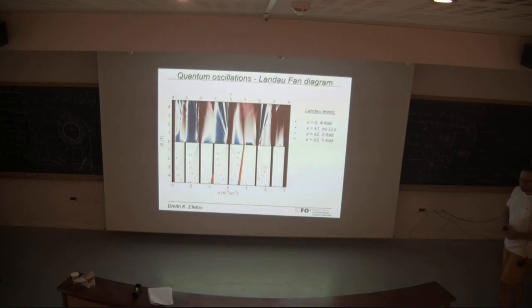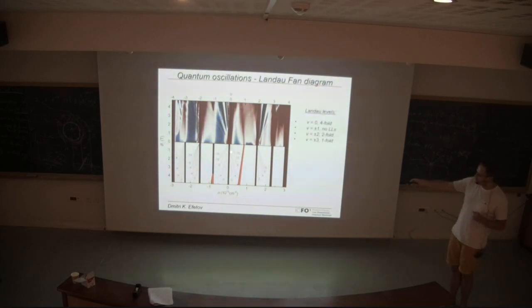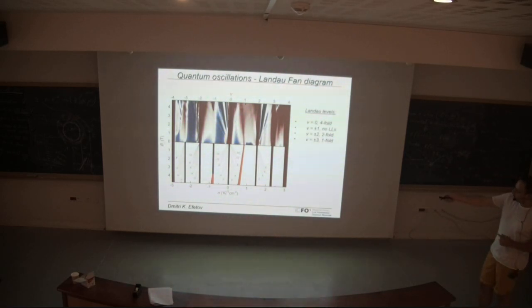So it's a debate. But what we can say, and this is also confirmed with other results, is that typically around charge neutrality we have mostly a fourfold degeneracy, but then if we look here, for example, at the -2 and +2 filling, we now observe a degeneracy of 2. So it follows the sequence of 2, 4, 6, 8, and also here -2, 4, 6, 8. That means that some of the degrees of freedom is broken. So it's either valley or spin, right? And probably it points to a picture where these bands here are in a spin singlet, and maybe valley is broken.